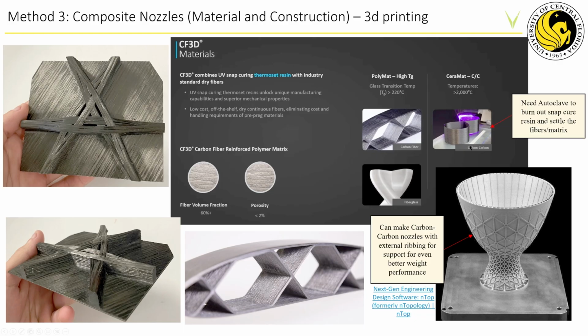And the cool part about this whole machine is that they're always getting volume fiber fractions of greater than 60% and the porosity of less than 2%. And you can actually see here some layups of this machine, and I actually have got some sample parts that you can see on the left here of it laying down, and you can actually see that this is how they cross fibers as you're going over the same area to make sure you're not getting a Z buildup in one area too much. But it's really cool because essentially the application for this is to make a nozzle like this, where you can lightweight the wall as much as possible, and then you can also go ahead and print specific directional supports with tow in the exact direction you need.